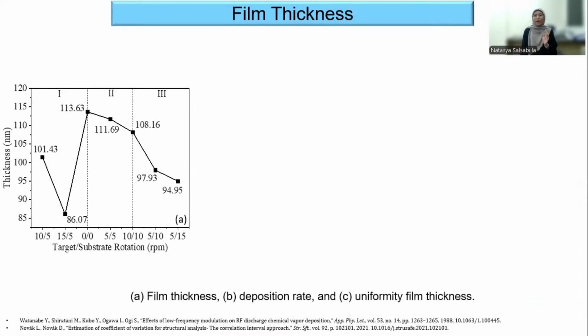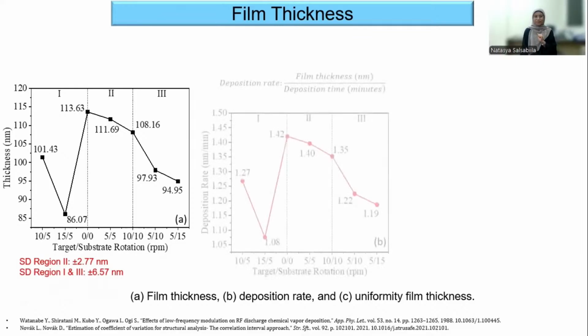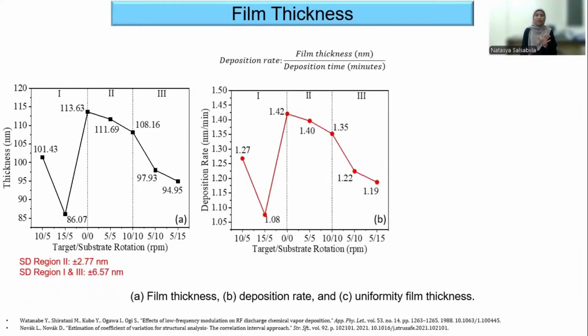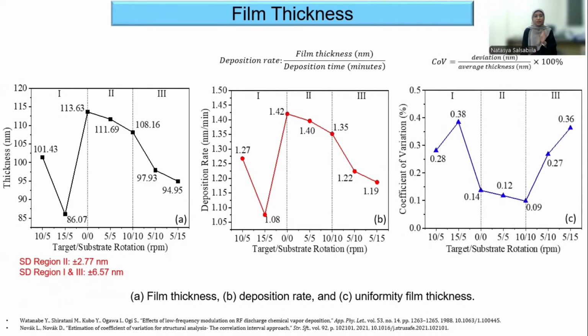From figure A, we obtain that in region 2, the standard deviation value is lower compared to region 1 and 3. This shows that in region 2, the film thickness remains relatively consistent with only minor fluctuations. Figure B shows the deposition rate, which also follows the same trend. The last one is figure C, which shows the coefficient of variation or COV value. Lower COV value means a higher uniformity, and again, the 10 per 10 RPM condition offers the best uniformity.